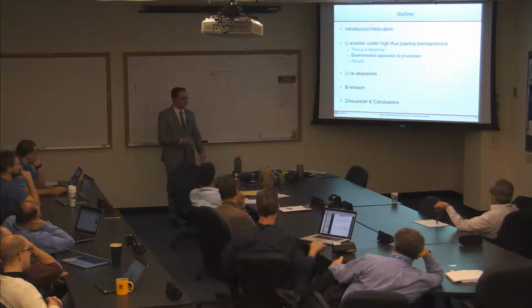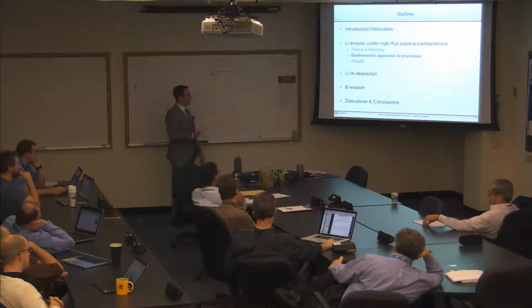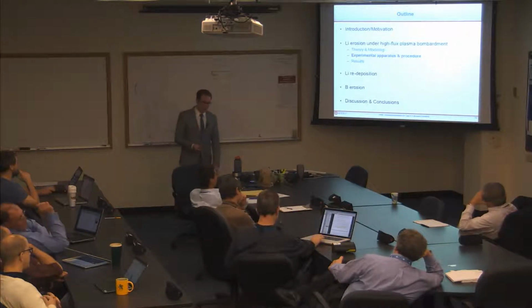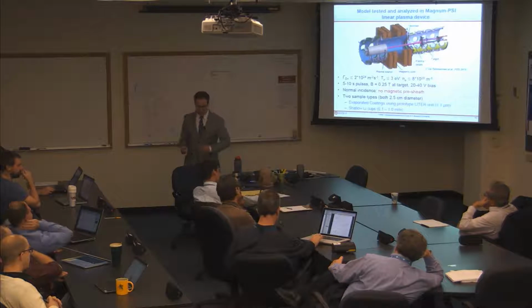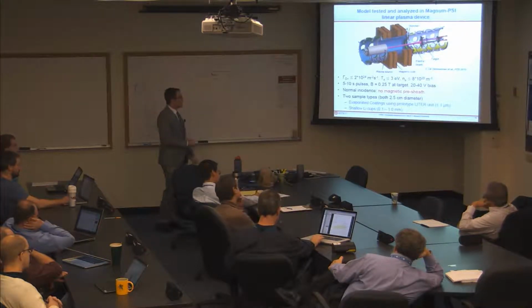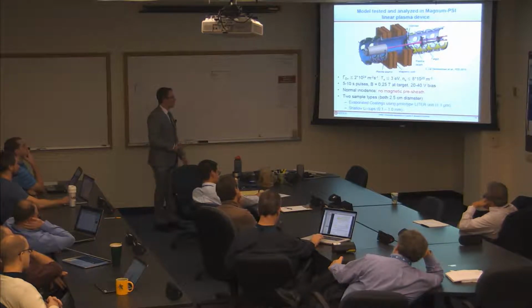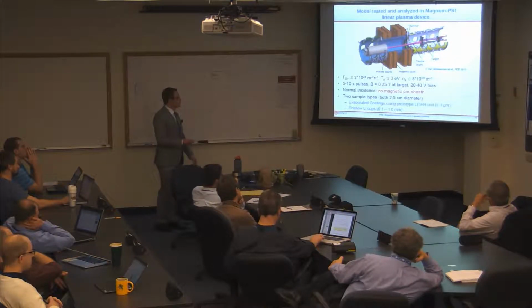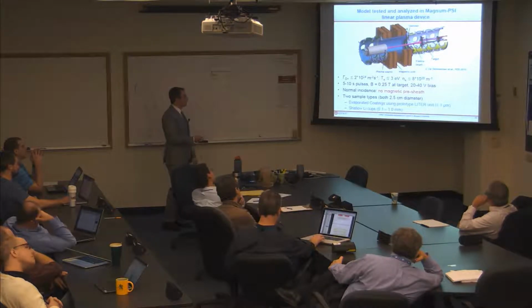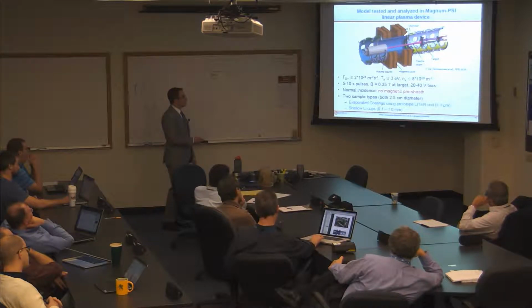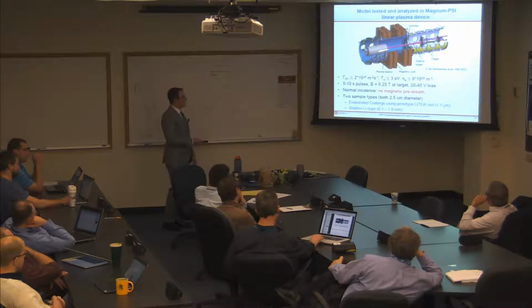Okay, so now we've talked a lot about modeling, a lot about theory, and now we're going to talk about the experimental apparatus and the procedure. The apparatus with which to test these predictions was the Magnum-PSI linear plasma device. It's shown here. This is a very large linear plasma device that can accomplish similar plasma parameters to what you find very close to the divertor strike point in a tokamak. Over here is the plasma source that generates your very high density plasmas. Then it shoots out in a beam that's collimated by these copper magnets here. It goes through a skimmer which pumps out almost all of the neutral particles in the plasma. And then the plasma beam strikes a target here.